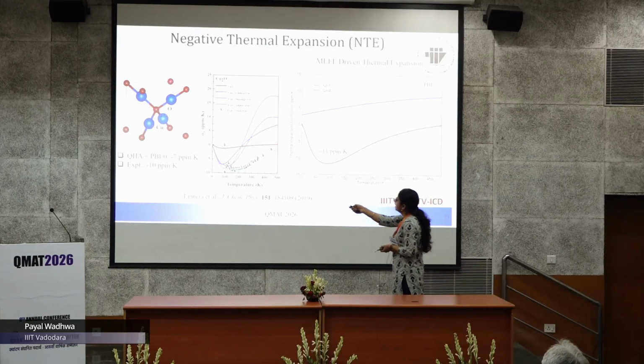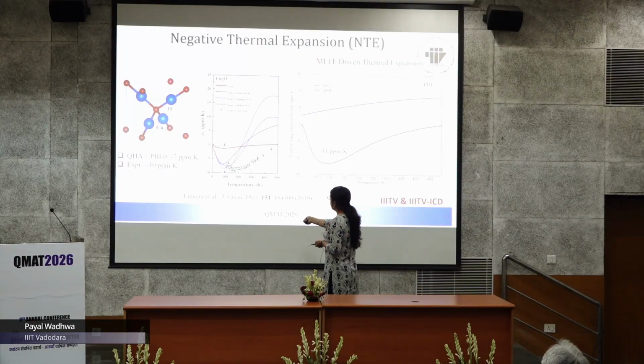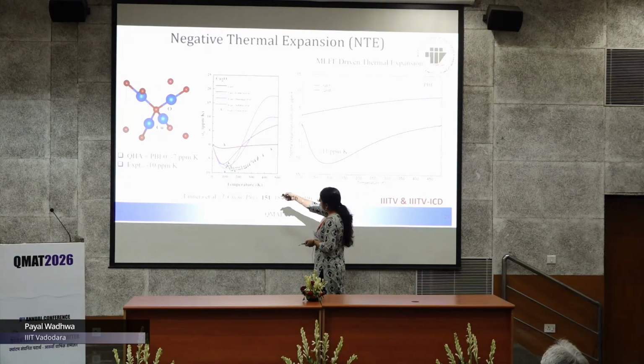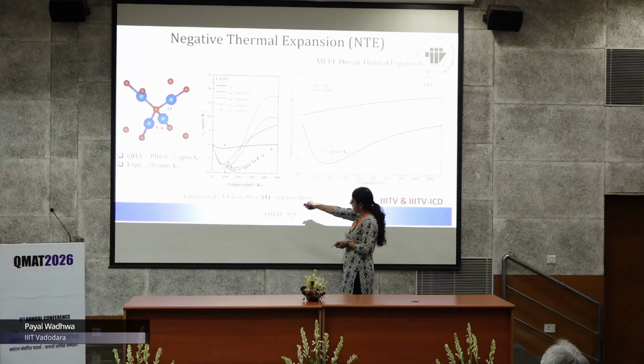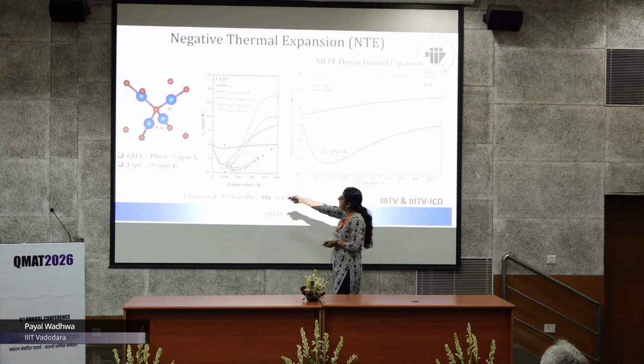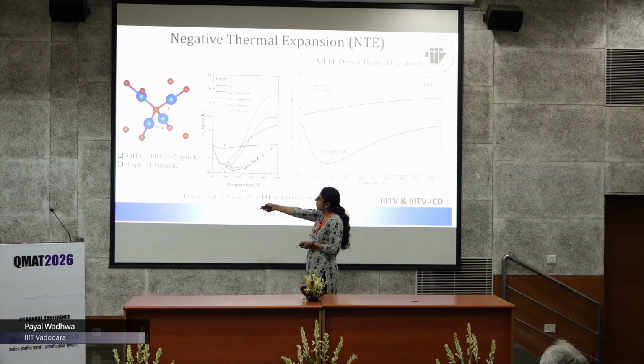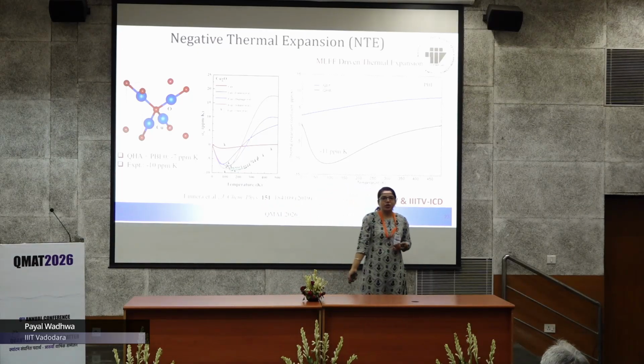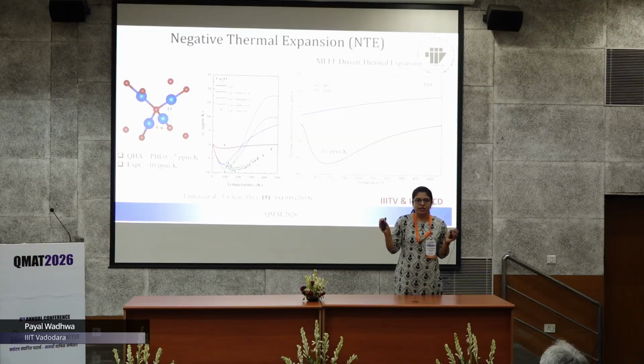You can see here, this is from the previous reports. We can see here that the volume first decreases and then increases, so it means it is following a negative thermal expansion. And previous theoretical studies have calculated these values using the quasi-harmonic approximation and PBE0. PBE0, you can imagine, is Hartree-Fock with 25% exchange, right?